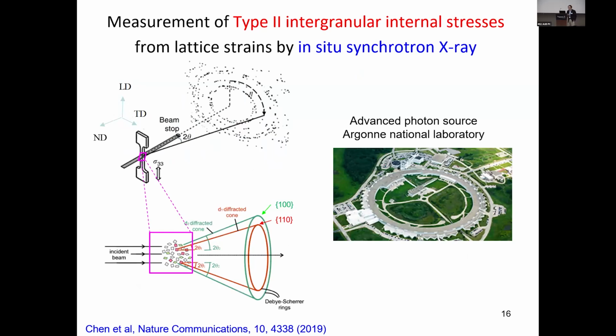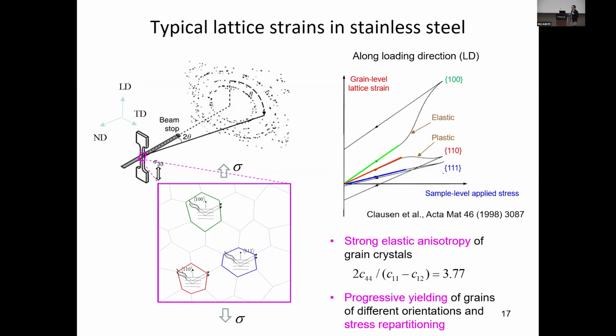To understand those internal stresses, we use APS in situ synchrotron X-ray diffraction to probe the grain-level and also the sub-grain-level internal stresses. We can measure the grain-level average lattice strain and further calculate the so-called stress for different grain families. As illustrated here, a set of grains at different locations but with a common orientation along the loading direction, like the 100 direction along the loading direction, we call them the 100 grain family. We could also have 110 and 111 grain families, right? So you measure the lattice strain of those grain families.